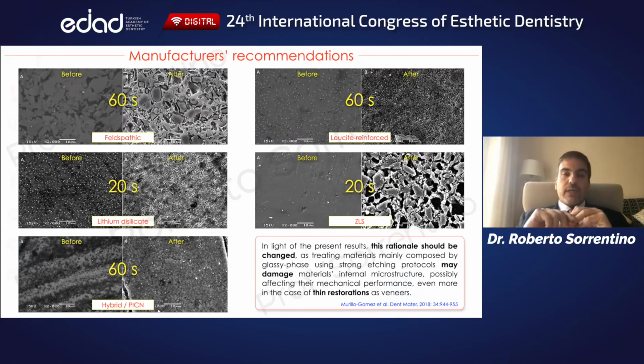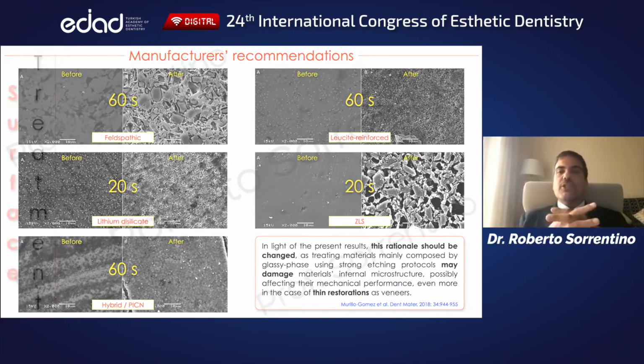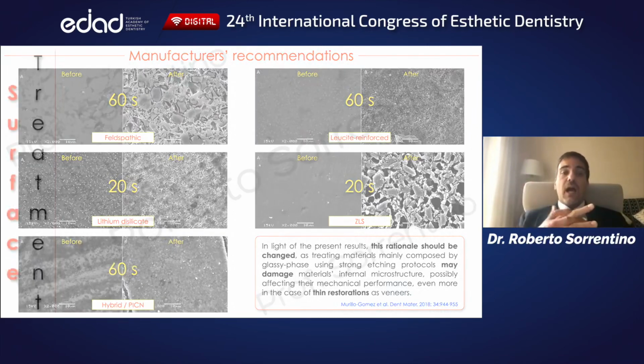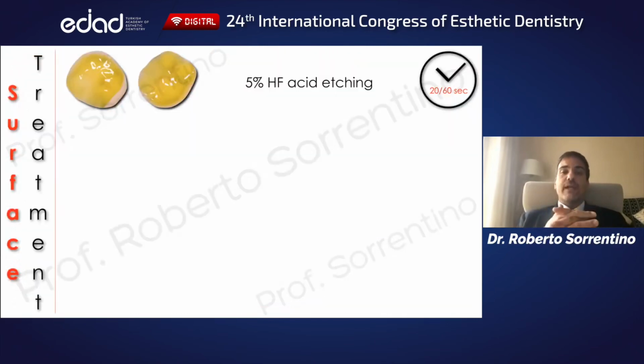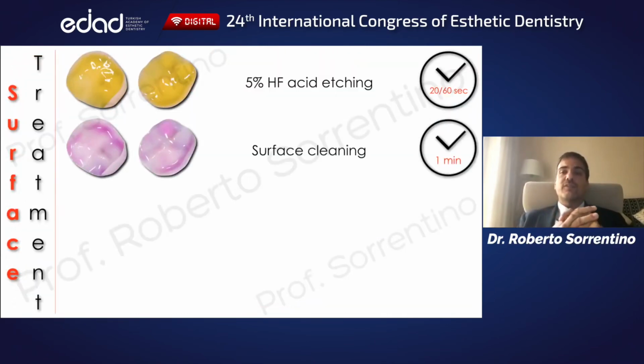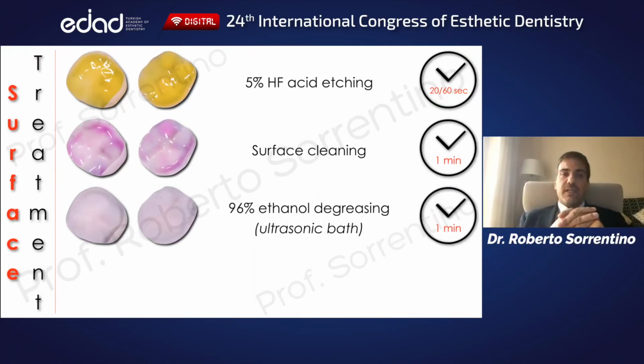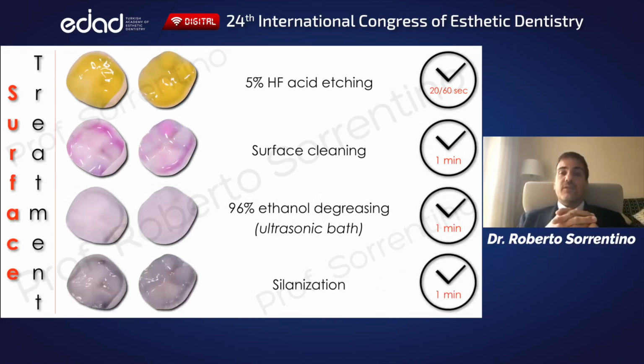So briefly, we can summarize the ceramic conditioning in 4 steps: hydrofluoric acid etching for 20 to 60 seconds according to the silica content of the material, surface cleaning by means of surfactants or dedicated cleaning solutions, surface ultrasonic degreasing using 96% ethanol, and finally the application of coupling agents such as MDP containing primers or silanes.